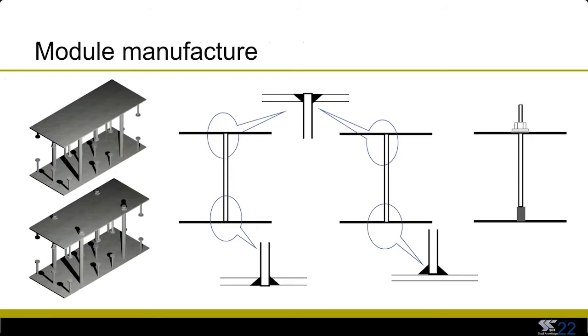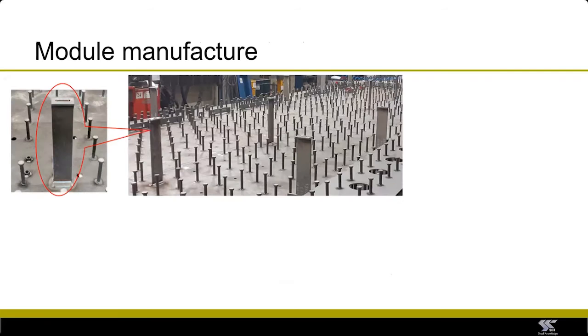And this was because for one of the plates, it's not permitted to have penetration through the plate for the pool structure. And a third method used a threaded bar, which was screwed into a coupler in one plate and then held down with a nut at the other end. And this was used at the edges of modules that were joined by dowel bars, because these tie bars had to be removed for the installation of the dowel bars.